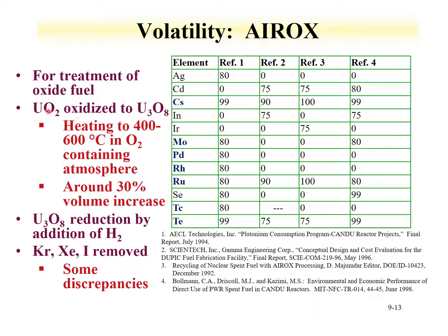If you heat the UO2 at 400-600 degrees in an oxygen-containing atmosphere, normal atmosphere, you'll get a volume increase as it goes from UO2 to U3O8. This exposes more of the grains to the surface. Any volatile fission products will be removed.